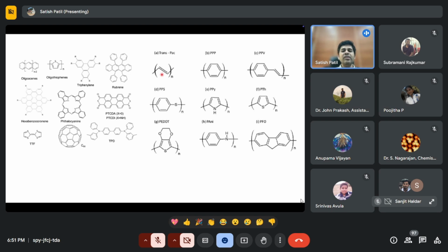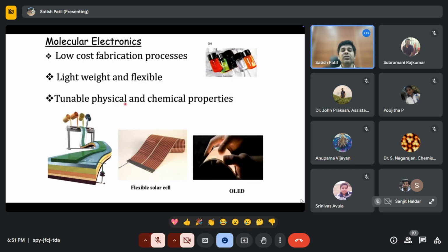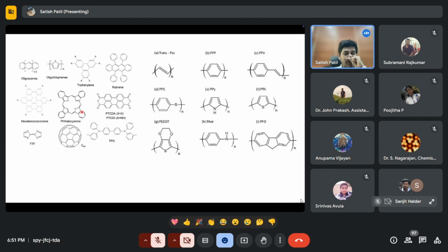For example, trans-polyacetylene and polyfluorene have a major difference in band gap. Here we have a band gap of less than 2 electron volt, and here the band gap is close to 3 electron volt. And in the case of polythiophene, if you use heterocycles, the band gap falls under 2 electron volt. So you can tune the property as an organic chemist. You can tune the physical properties, as I mentioned in the previous slide. Tunable physical and chemical properties. That is very hard to do in the case of silicon. You can dope it, you can change the band gap a little bit, but you cannot tune the property like this.